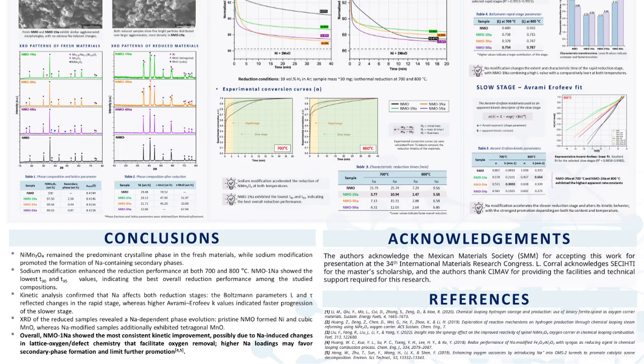In conclusion, nickel-manganese oxide remained the predominant crystalline phase in the fresh materials, while sodium-containing secondary phases were detected in the modified formulations. Sodium modification significantly enhanced reduction performance at both 700 and 800 degrees Celsius. Among the studied compositions, the 1% sodium formulation showed the lowest times required to reach 90 and 95% conversion, and therefore the most consistent overall kinetic improvement.